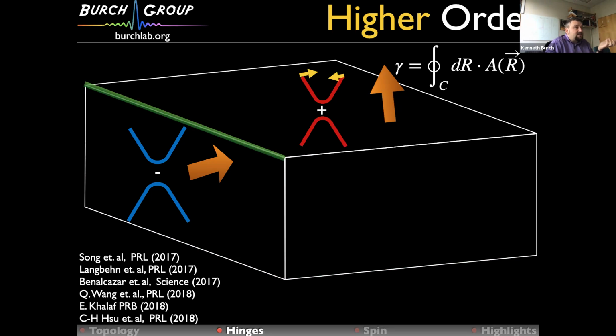And that zero energy state is really like a new version of the bulk boundary correspondence, telling me that I have a new kind of topological system. So if you want, you can think of it like, what I've done is to go from the atomic limit to a sort of a Berry dipole. That's not the right words, but anyway, to a sort of dipole, and then to a quadrupole. And because now I have a quadrupole, instead of getting surface states, I'm getting these one-dimensional modes. So this was a nice theoretical construction done by a couple of different groups, sort of in parallel.